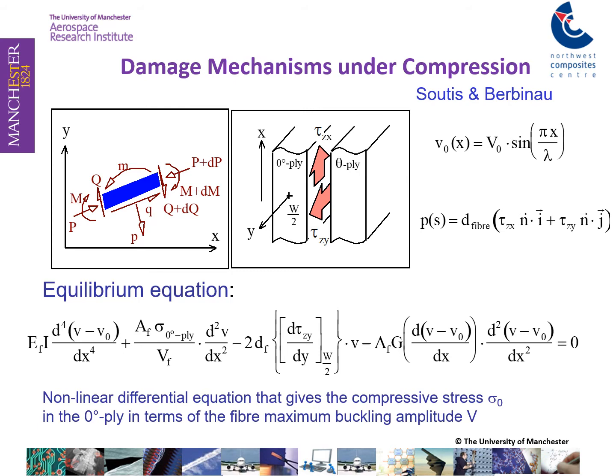And this is a function of the fiber properties, the modulus, the radius, the initial waviness, the fiber volume fraction, taking into account the interlaminar shear stresses, especially the tau zy, which can increase the fiber waviness and as a result reduce the stress at which fiber microbuckling will initiate. And the equation also takes into account the entire non-linear shear response of the matrix, which again has a huge impact on the fiber stability, especially when the matrix provides the lateral support to our fibers.